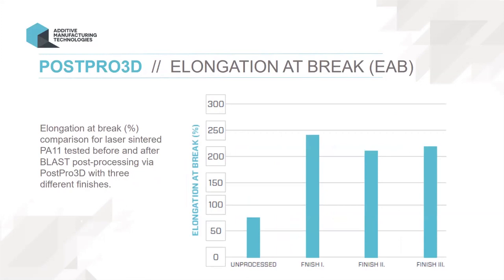Nylon 11, when you're producing parts with printers like 3D Systems, you can get maximum elongation at break properties of around 50 to 60% if you really are using the parameters that David has developed for performance. And after our post-process, that elongation at break will jump to sometimes 200, 225, 240% elongation at break. So yes, we do that without necessarily modifying the modulus. You may say, well, you're softening the parts, so you're stretching them more. That's not the case. We are retaining the modulus, which is critical. You cannot do that with just any single chemistry or any single process.